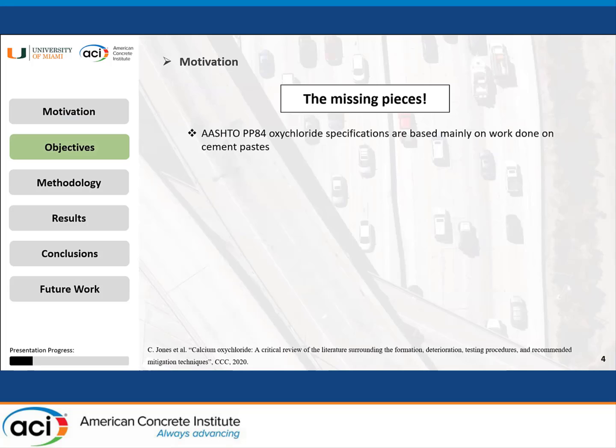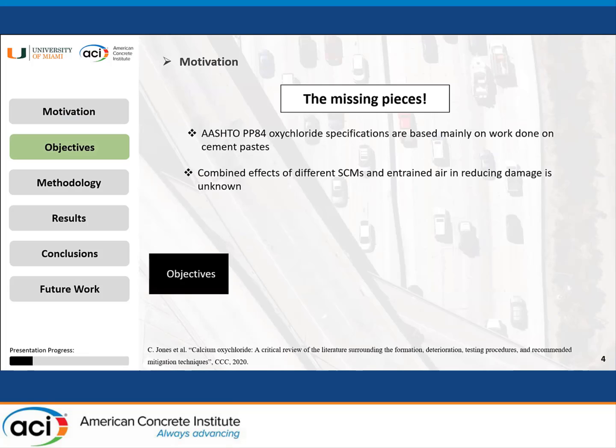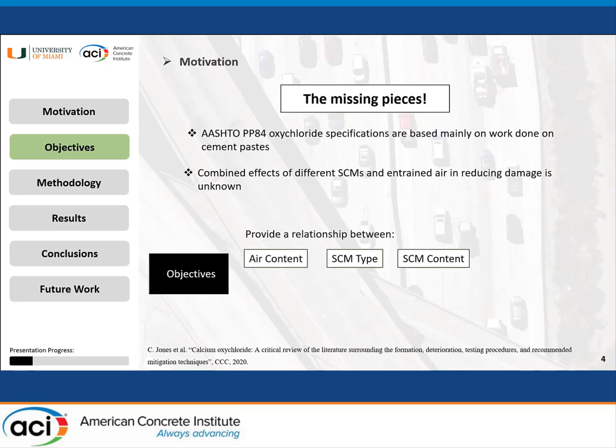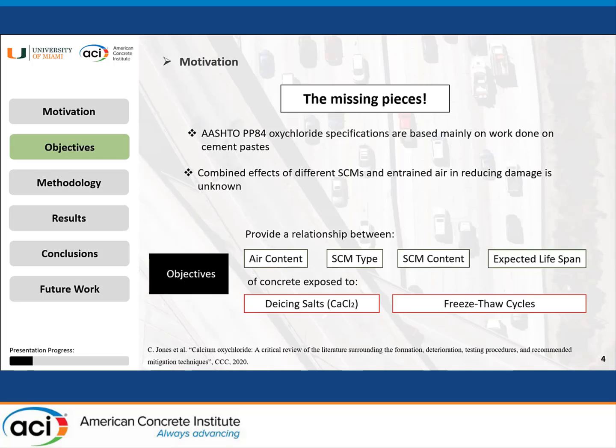But what are the missing pieces in this criteria? First of all, the AASHTO PP84 oxychloride specifications are mostly based on work done on cement pastes. In addition to that, the combined effects of different SCM types and entrained air in reducing this type of damage are still unknown. So that's why our objective in designing this experiment was to provide a relationship between the air content, the SCM type, the SCM content, and the expected lifespan of concrete exposed to de-icing salts, which is calcium chloride in our case, and freeze-thaw cycles.